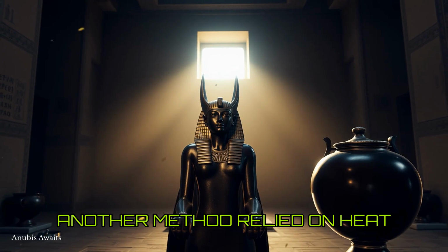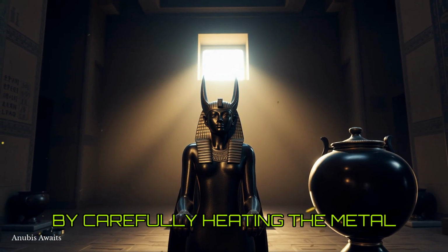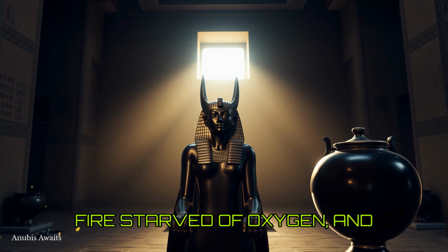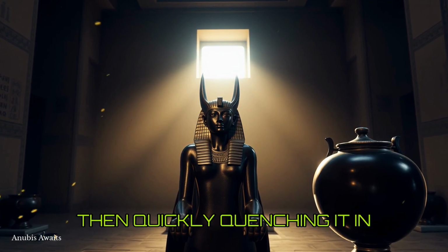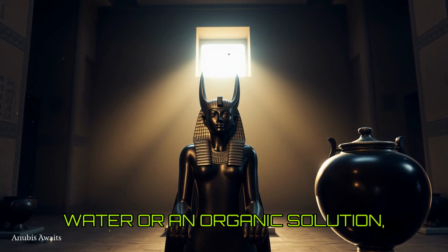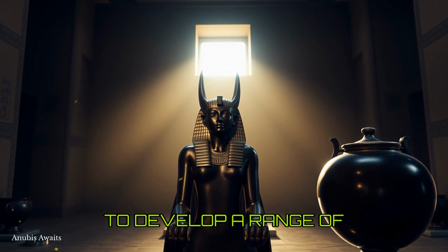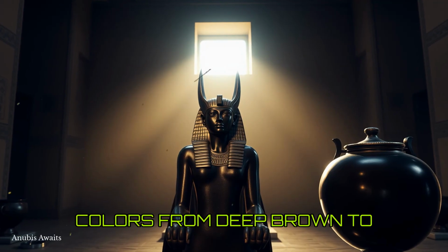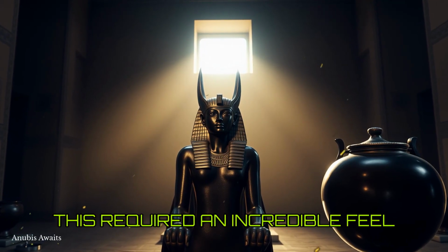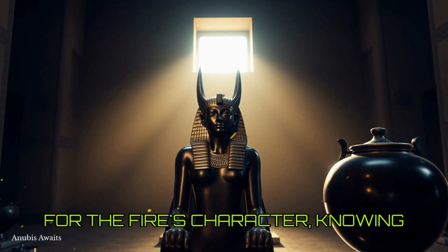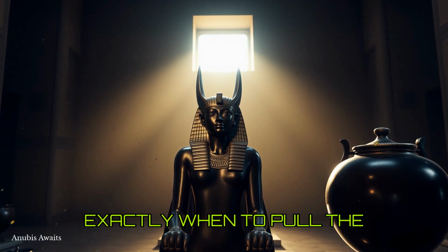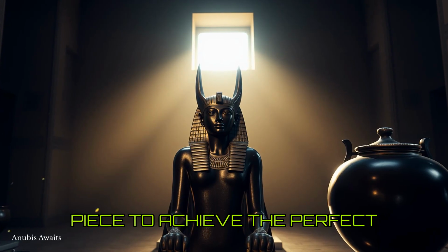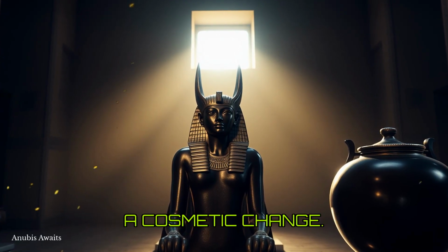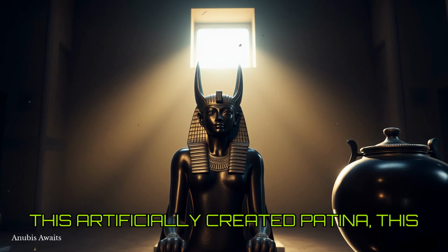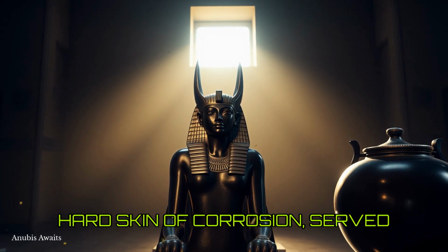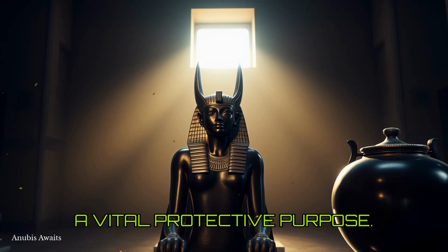Another method relied on heat alone. By carefully heating the metal in a reducing atmosphere, a fire starved of oxygen, and then quickly quenching it in water or an organic solution, they could force the metal to develop a range of colors from deep brown to a bluish black. This required an incredible feel for the fire's character, knowing exactly when to pull the piece to achieve the perfect shade. The result was not just a cosmetic change. This artificially created patina, this hard skin of corrosion, served a vital protective purpose.